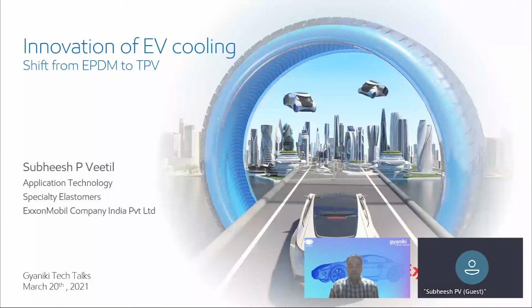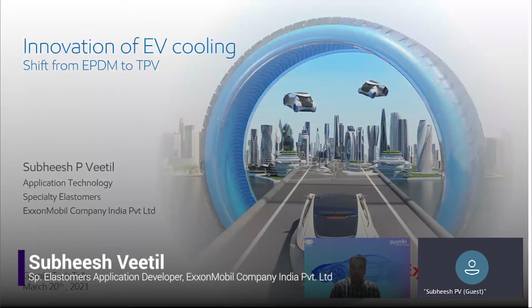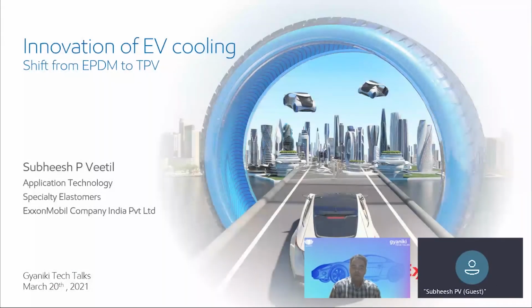No, there are absolutely no limitations. We can go to hose in a diameter as small as 5 millimeter. You can extrude the parts as thin as 0.5 millimeters. So there are no limitations. And in fact, this is the advantage of Santoprene TPV, because you can make parts as thin as possible, which is not possible with an EPDM compound. With EPDM, you need to meet a minimum thickness, for example 2 millimeter or so, to meet the requirements, whereas Santoprene can go down as low as 0.5 millimeter.